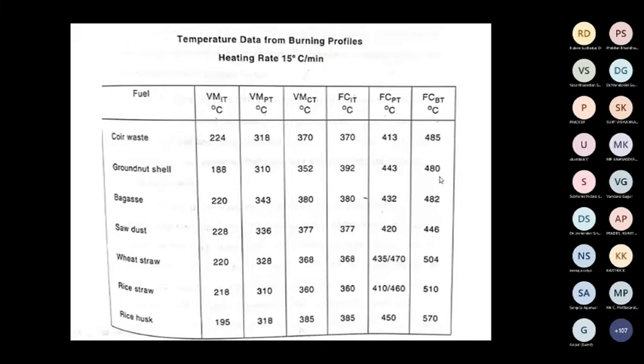So these are all the temperature data of the burning profiles for all the biomass fuels. Initiation of volatile matter combustion starts around 192 to 220 for all the fuels. Then maximum volatile matter combustion is around 320. If you see VM completion and fixed carbon initiation, they are almost the same, 370, 380, except groundnut shell. For groundnut shell, there is a time lag between VM combustion and fixed carbon combustion. Here, VM ends at 352 and fixed carbon starts again around 392.